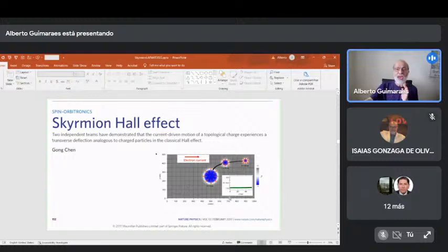With skyrmions, they move as shown in the previous slide, with the current applied. Now here I'm drawing your attention to the fact that they do not propagate in a straight line. They move away from the axis, and this has been called the skyrmion Hall effect. Unfortunately, this animation shows the text of this article, which will not appear now. The animation makes a parallel between the skyrmion Hall effect and the Magnus effect.